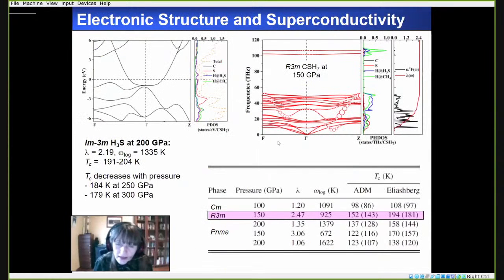The TC and electronic structure of the phases were calculated using density functional theory calculations. And the most important point to take away from here is that the electronic structure near the Fermi level arose from the sulfur and the hydrogen atoms. And therefore, the SH framework is what is going to be responsible for the superconductivity. And here I show the estimates of the superconducting critical temperatures that we obtained, with the highest calculated TC value on the order of 190 Kelvin at 150 gigapascals.